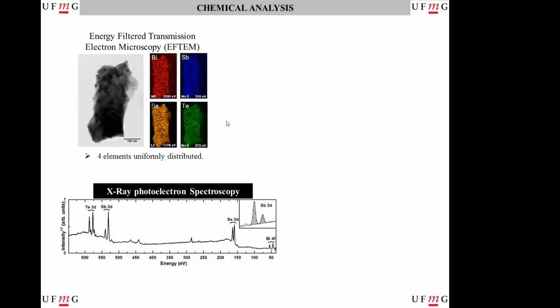Before going to the ARPES results, we did a chemical analysis. Here we have an electron microscopy image of a grain in our powder sample, and you can see that the four elements are uniformly distributed in our sample. We also have an X-ray photoelectron spectroscopy measurement here, where we did a photoemission spectroscopy using an X-ray tube, and we can identify the peaks of each element